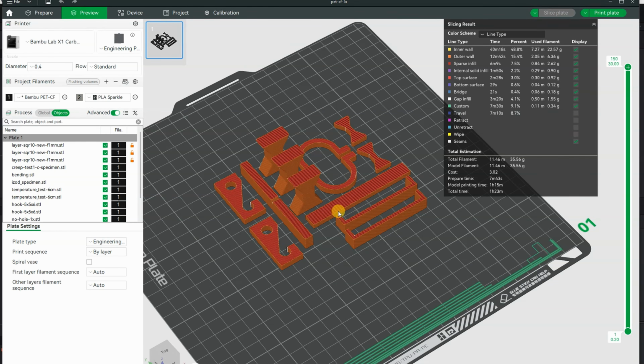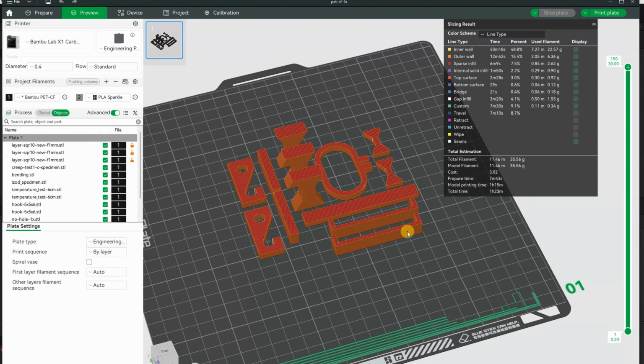For the bending test, the object is the same as before, but I will use different equipment. 64 mm is the distance between supports. For the temperature test, I will have 2 objects and one of them will be annealed. For the creep test it is the same test object, but I will use a little bit different weight. I don't want to use 1.25 kilograms, lighter or heavier, at this moment I'm not sure.